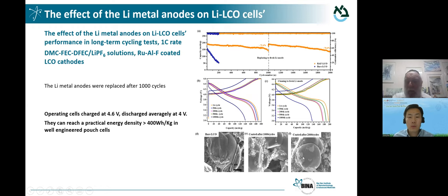The post-mortem analysis showed that after hundreds of cycles, no cracking. This is an untreated material which shows cracks. Our material is smooth. This is a cross-section that shows that we maintain the integration of the particles. And after 1,000 cycles, we saw some capacity fading. We simply replaced the negative electrode, continuing with the cathode, and we could come up with 1,000 cycles more. So this demonstrates stabilization of both negative and positive.